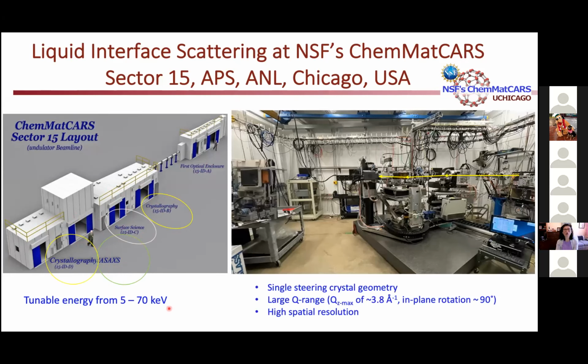Here we show our liquid interface scattering instrument that was built in 2002. It's a single crystal steering geometry. It has a quite large Q range—QZ can reach 4, although we never even reached above 2 because there's just no scattering from the samples. The in-plane arm can rotate at 90 degrees, and this instrument has a high spatial resolution.